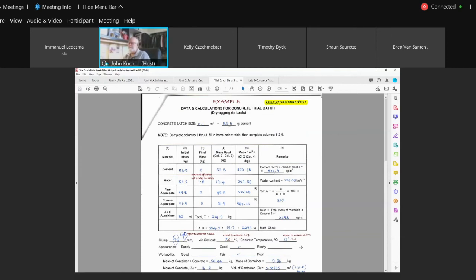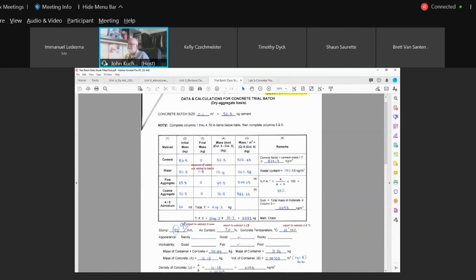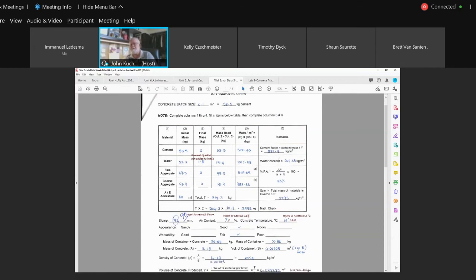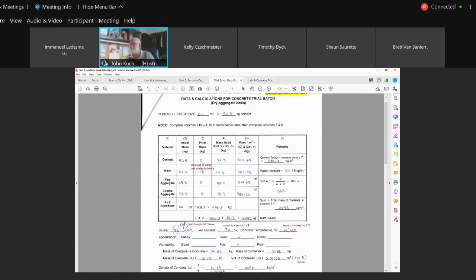That's why yield is important. So if you're going to design for a little bit more than 1 cubic meter, you might go 1.03. Make sure that cement is based on 1.03. So here, that's why the cement factor, and that's what is referred to, cement factor, or cementitious factor. Cementitious would take into account having the fly ash as part of your cementing material. Like I said, this example just doesn't have fly ash in it. So here you can see then that they're not shortchanging them on the cement, but the opposite could hold true.